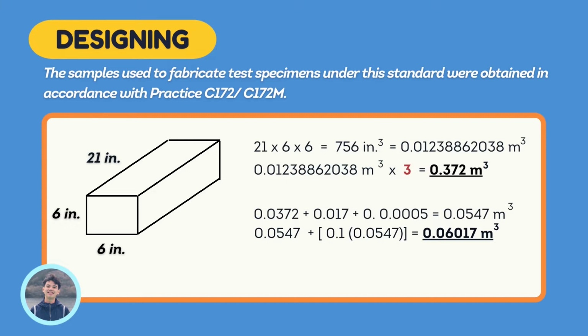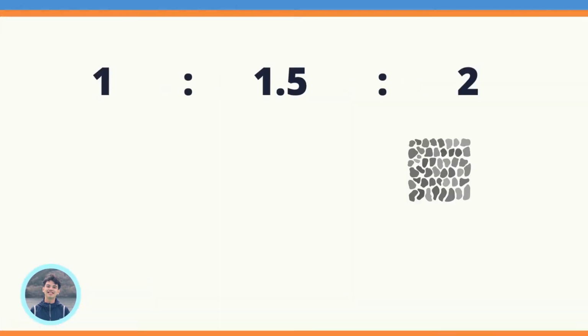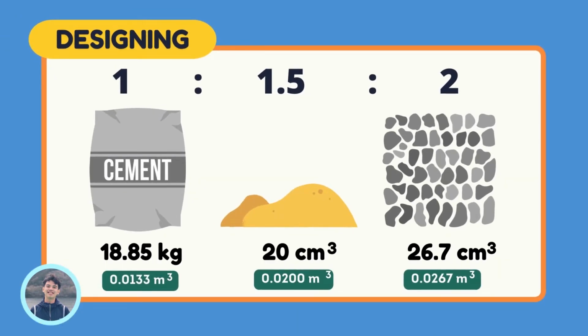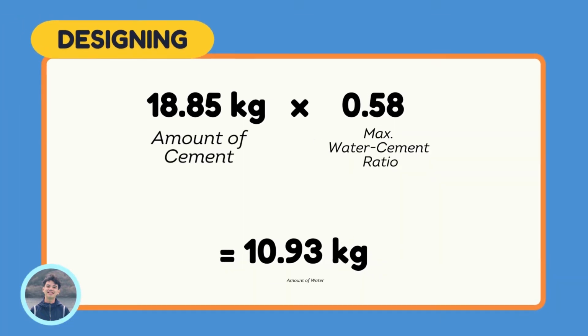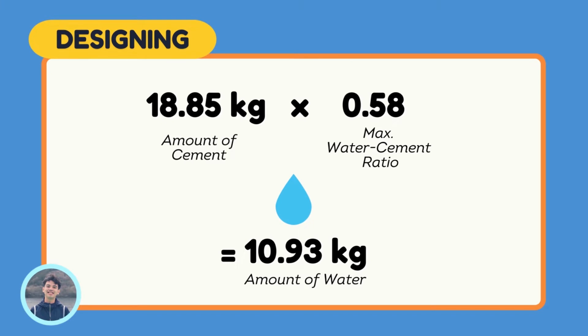To determine the amount of concrete mix required to conduct the activity, the volume of the beam mold was measured and multiplied by the number of beam molds to be filled. The value was then added with the other experiments to come up with the total. The total was then added 10% of its value and divided into parts with respect to the ratio, which was 1:1.5 and 2. For the amount of water, the value for cement was multiplied by the maximum water-cement ratio for the Class B concrete, which is 0.58 in accordance to the DPWH Blue Book.